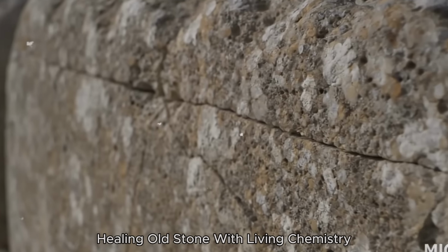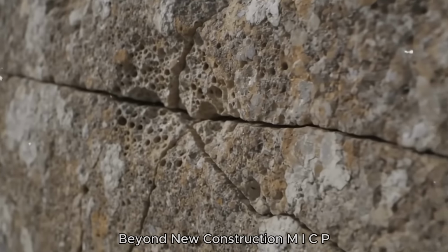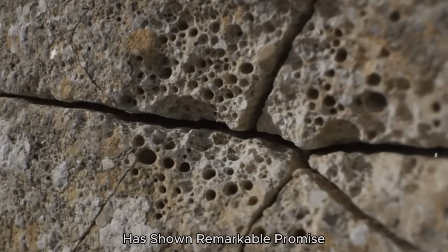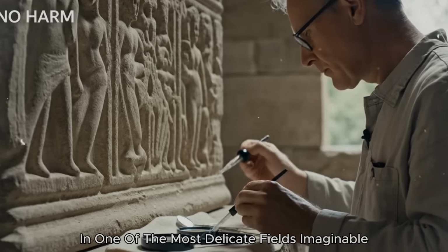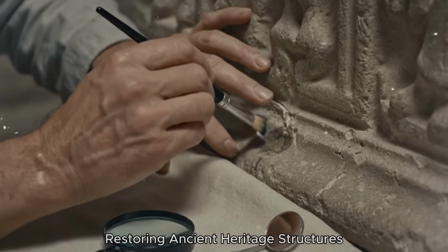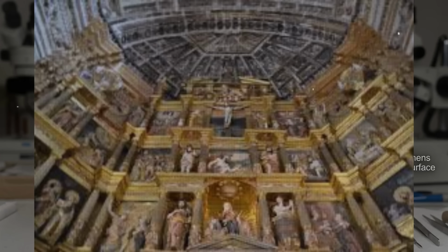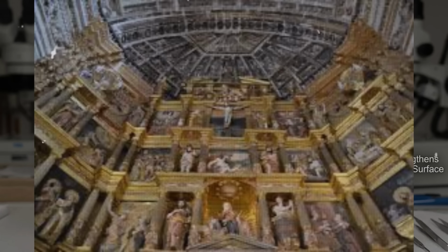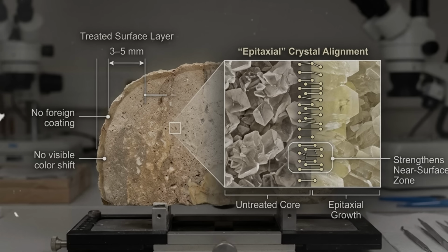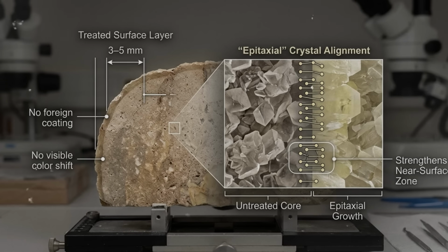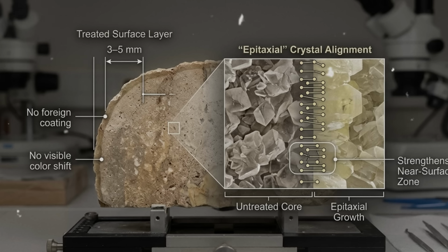Healing old stone with living chemistry. Beyond new construction, MICP has shown remarkable promise in one of the most delicate fields imaginable, restoring ancient heritage structures without damaging them. Researchers in Granada, Spain, applied bacterial calcium carbonate treatment to 16th century stone monuments, including the Hospital Real and San Jeronimo's Monastery. The results were striking. The treated stone gained measurable hardness improvements in the first 3 to 5 millimeters of depth.